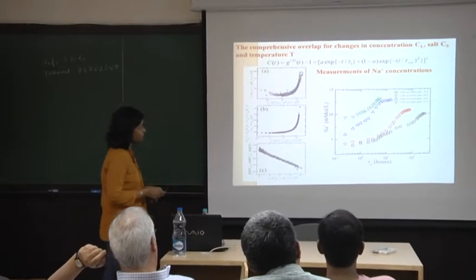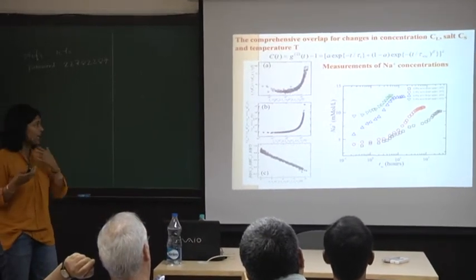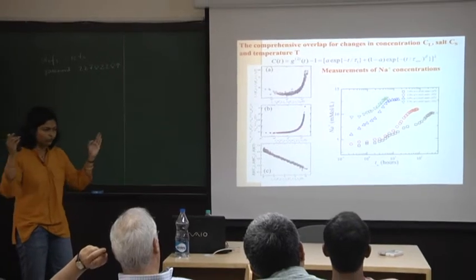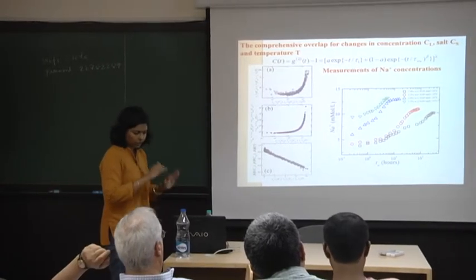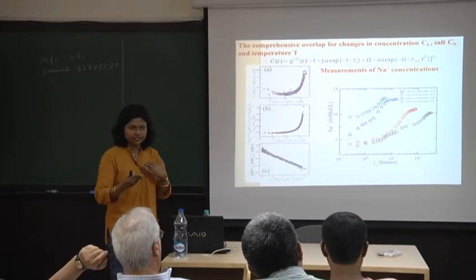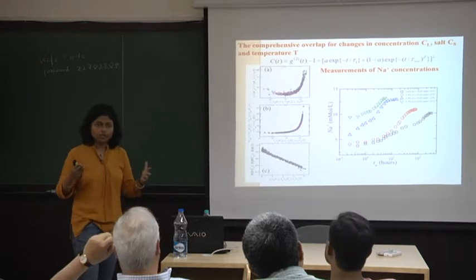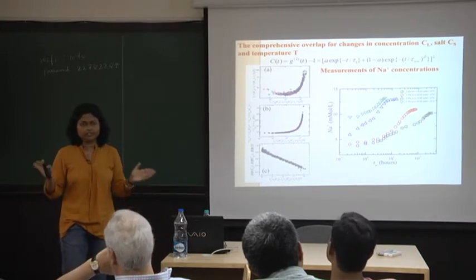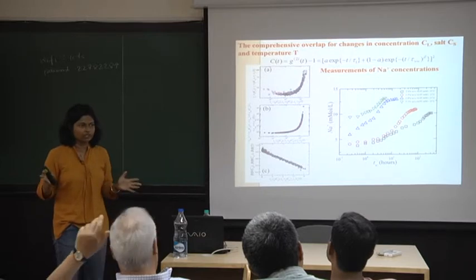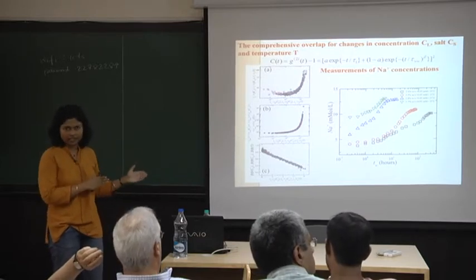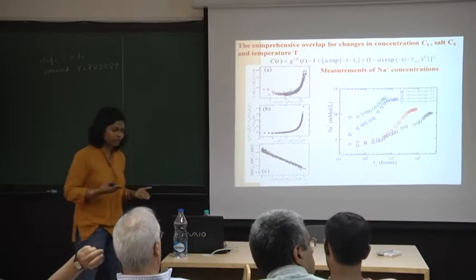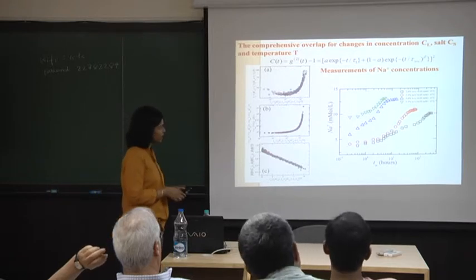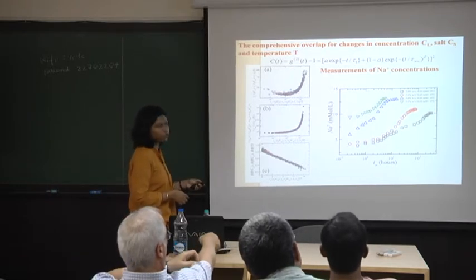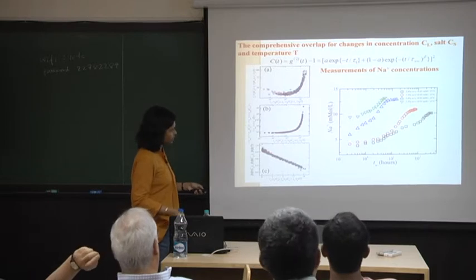We've measured sodium ion concentrations. So remember, you've put in your salt, you've put in whatever the concentration be, you've increased your temperature. Whatever you do, the net result of all these actions is to increase the number of sodium ions in the solution. In our case, that increase in the sodium ion concentration happens gradually, right? So that is what we measure with a sodium ion meter. Okay? So this is versus the age.